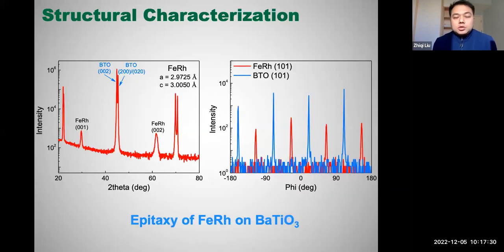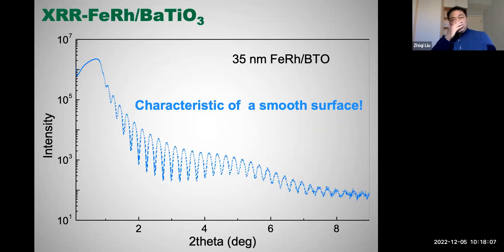And then we try to grow this metal on ferroelectric oxides. For example, here we use barium titanium oxide, BTO. It's a very typical ferroelectric oxide. Because of the relatively good lattice match, we can easily grow iron rhodium, this metal, onto BTO. From this 360-degree phi scan, we can see this is an in-plane 45-degree rotation epitaxy. If we make the growth slower, we can get a relatively smooth surface. For example, the growth mode could be tuned into a quasi two-dimensional growth.